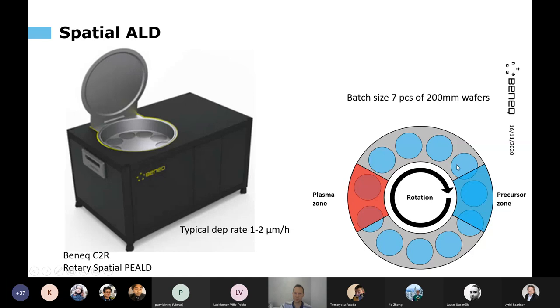And then the substrates are passing through these regions. So they are on a turntable that is being rotated. And rotation is kind of easier or faster to do than pulsing the gases and purging the gases. And we can run this with much higher deposition rates. So typical deposition rate with this kind of system is 1 or 2 microns per hour, not per day, but per hour. So these are already reasonably high deposition rates compared also to other thin film techniques.